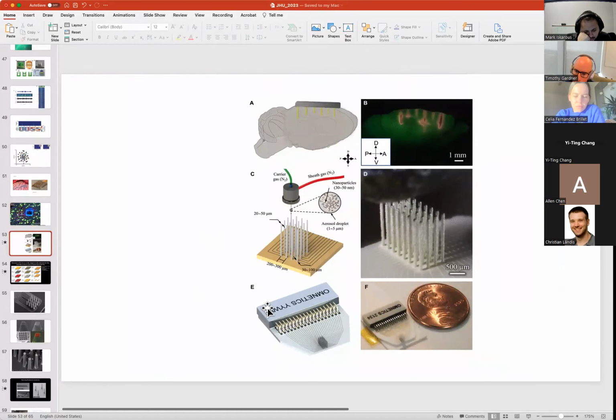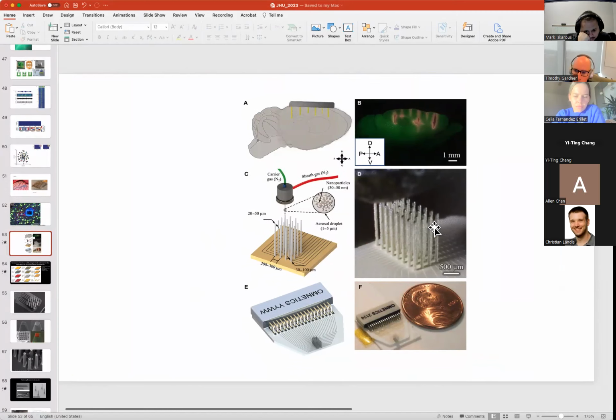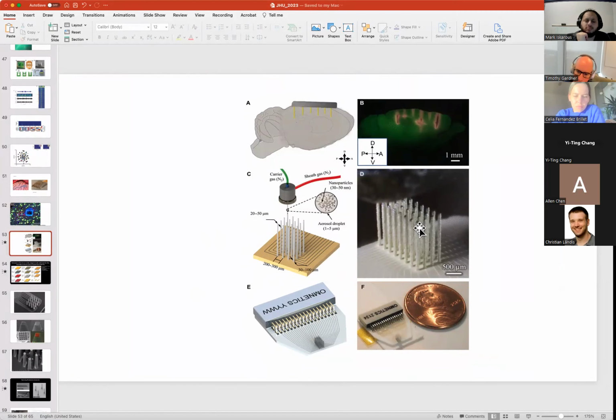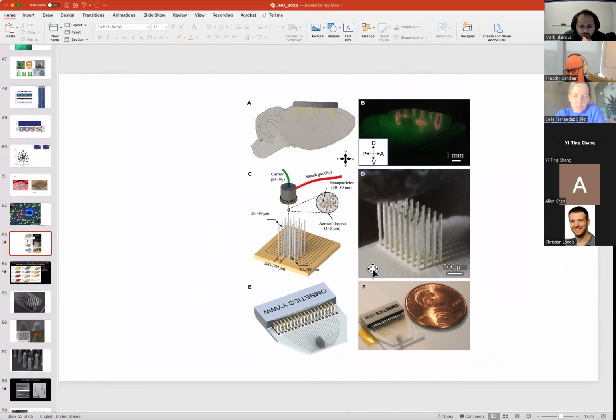We were excited by work that was published by Carnegie Mellon. This is the Carnegie Mellon array. It's a 3D printed electrode array that uses an aerosol droplet of metal that can build 3D arrays with a very different process than the Utah array. And we asked if we could do something similar with 2-photon lithography. The reason that's highly desirable is that 2-photon lithography resolution is another order of magnitude better than what you could do with aerosol jets.